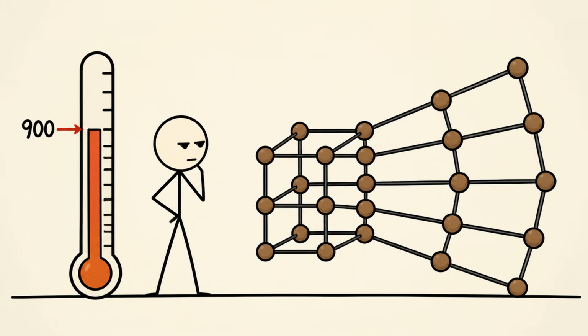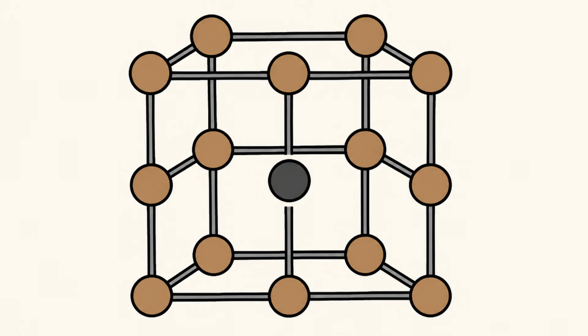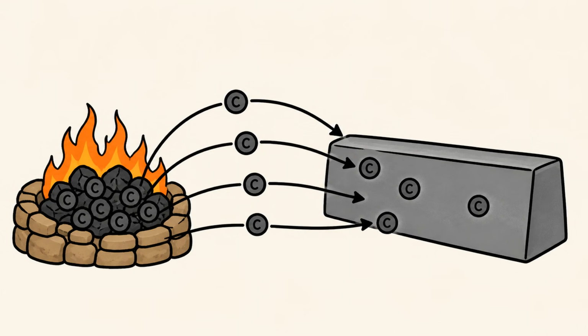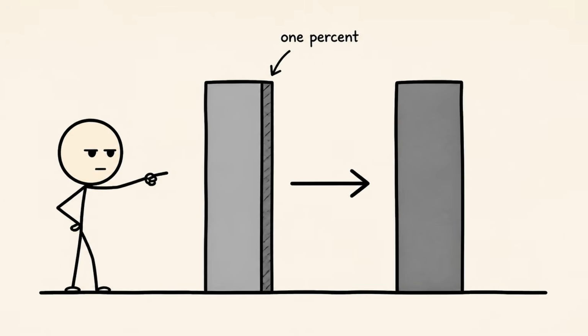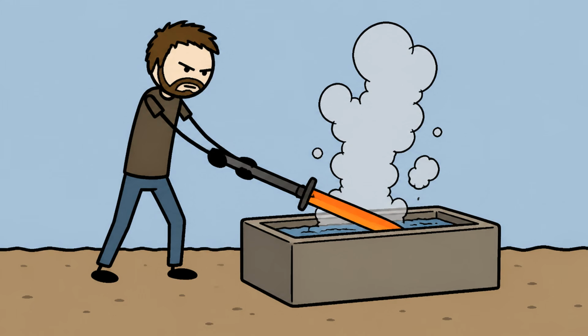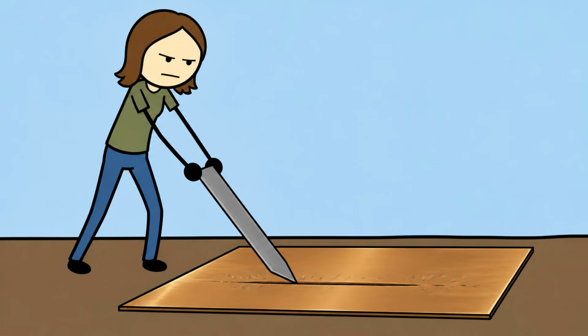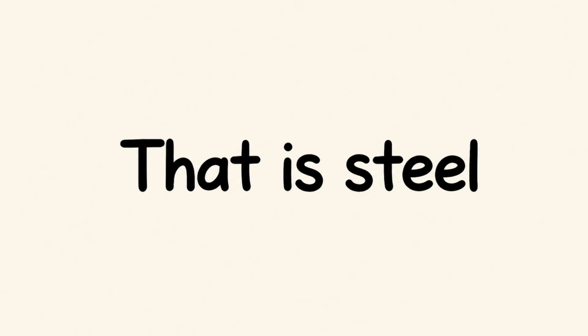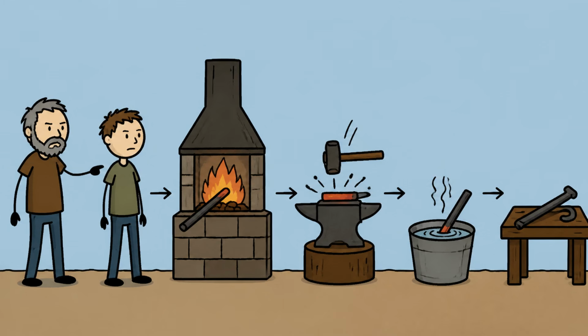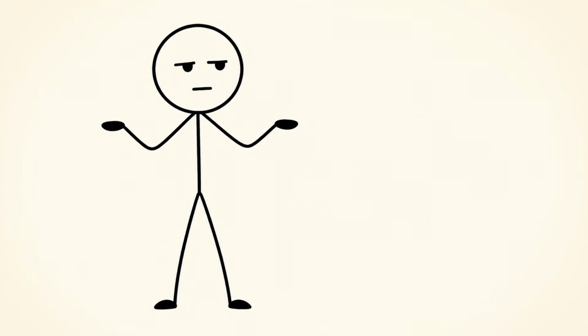Above about 900 degrees, the crystal structure of iron opens up, and the gaps between its atoms happen to fit a carbon atom exactly. Carbon walks out of the charcoal and into the metal. Less than 1% by weight changes everything. Cool that fast in water, and the structure locks hard enough to scratch bronze without effort. That is steel. It was found by men who could teach the recipe perfectly and explain none of it.